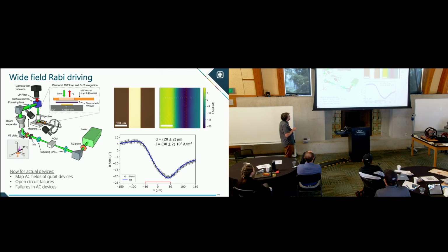This is actually a simple device. This is the microscope that we built where we use permanent magnets to get higher magnetic fields. I think Peter was mentioning something like this, that you can shift the resonance that you're looking at and coupling into these AC fields by shifting the Zeeman effect. This allows us to go from 2.87 gigahertz down in frequency, down to hundreds of megahertz, tens of megahertz, with the 0 to -1 transition, or actually up for the 0 to +1 transition from 2.87 gigahertz to whichever frequency we can drive. So this comes into that dynamic range of NVs too, right?